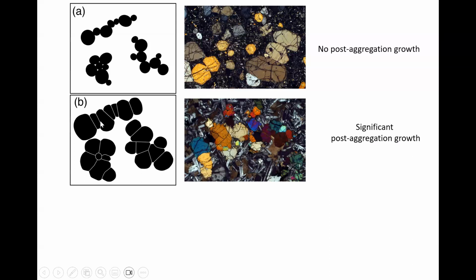And the original diameter of the particle is shown by the small axis here, because it can only grow out sideways. And then small grains that are trapped or completely surrounded by other grains are just going to stay the same size. Okay, so this is what we see in the sill from Skye, where the olivine clusters were kept suspended for a long time.